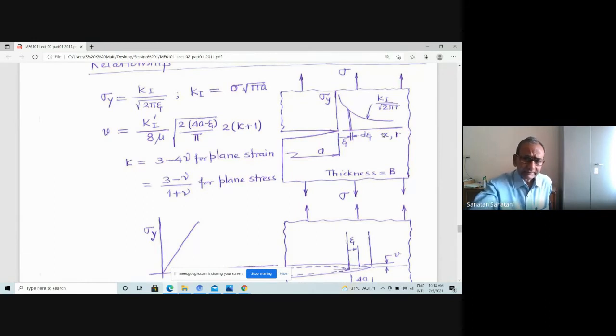But then one thing is there, that this sigma y stress, if you try to plot it against R, is actually going in proportion to 1 by root R, and therefore this is the variation. So it is very high at the crack tip and gradually reducing with distance R. And therefore you see that this sigma y stress on the crack line is given by K1 by root 2 pi R, with theta equal to 0.